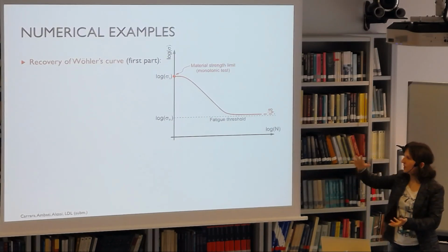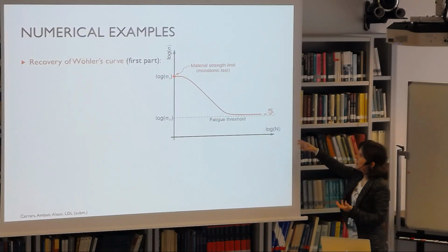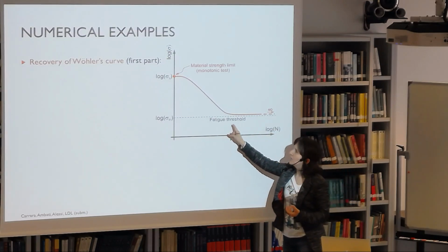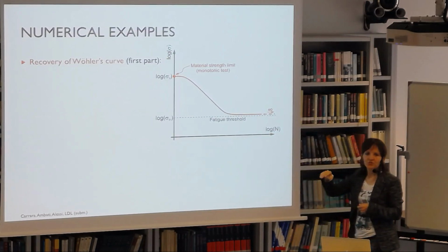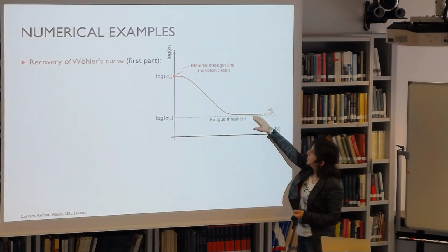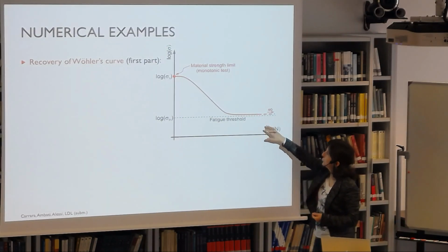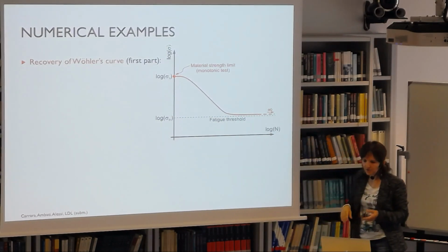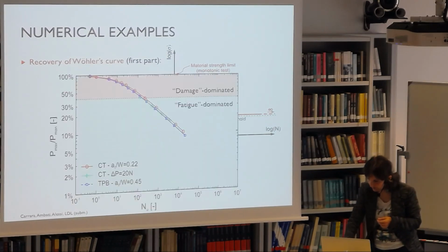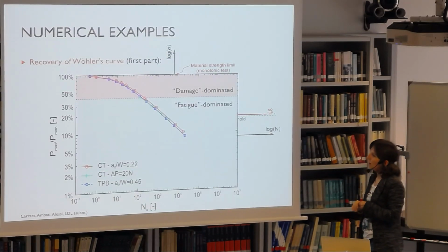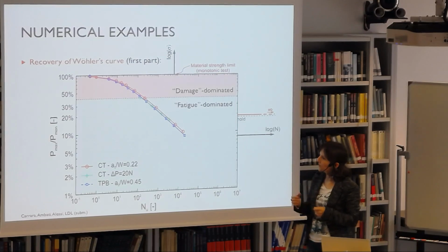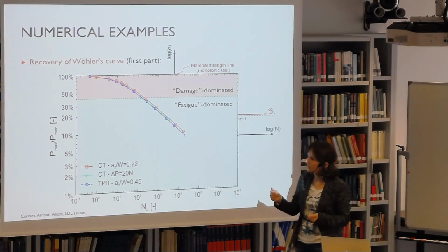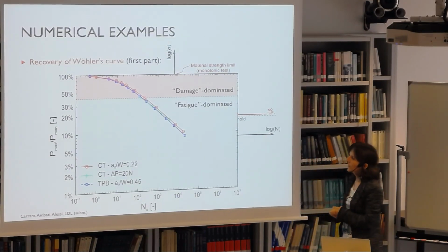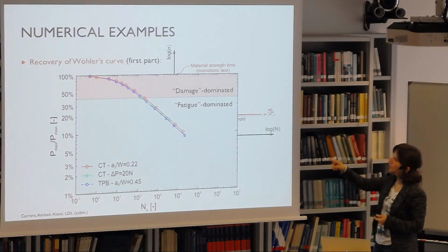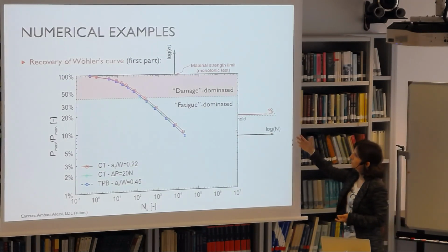then you can sustain more and more cycles, until in some materials you can have some fatigue threshold where, if the stress is smaller than this threshold, then you can have infinite fatigue life. But as I said, this has also been updated in recent times. So now our numerical experiments, both with CT, so compact tension, and with three-point bending specimens, show a behavior that is very close to what I just showed you.